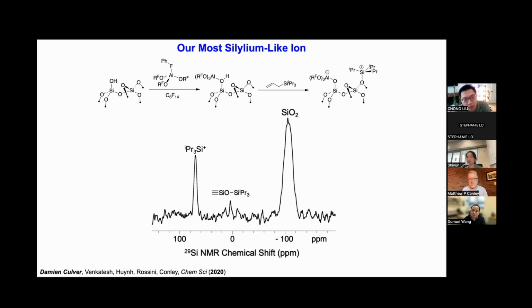So you had mentioned XANES and XAS, and I had alluded to that as well. You could do XPS is another method that can work for these. Though I must admit, it's a technical issue with this particular class of sample, because you always expose it to air at some point. And that kind of eliminates that as a useful method in most cases. There's also EPR. If you have spin active materials, you could do SQUID, just like you would do for organometallic single molecule magnets. Most of the analytical techniques that I would be familiar with as a molecular inorganic chemist do translate pretty well to the solid state, with various complications here and there.